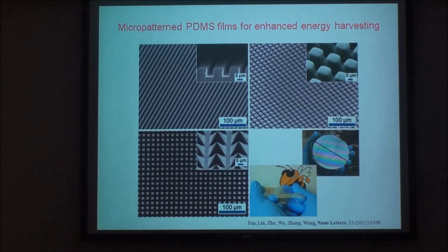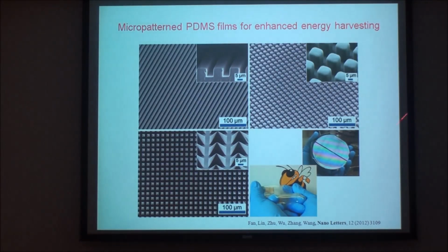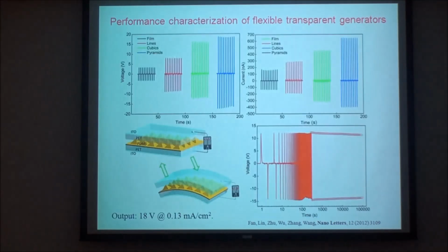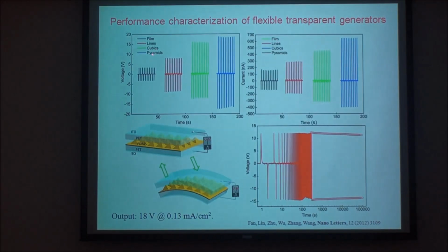Of course, through surface engineering you can do patterning, using lines, square-based, or pyramid-based features, and you can increase the output. You can make it completely transparent and put it on a wafer, etc. You can see that with the pyramid features introduced, the output voltage increased by a factor of 4, and current increased by a factor of 4, and so on. You can use a lot of surface modification to improve it.